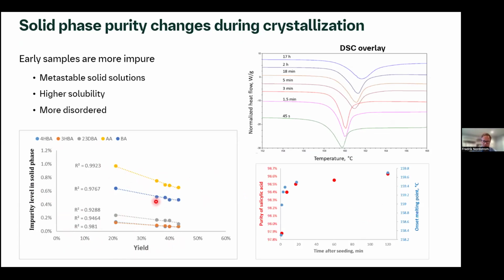And you can take these samples, right? We have solid samples here. So we analyze by HPLC, but you can also do a DSC to see what actually happens to the melting temperature and melting enthalpy. And here you see that the early samples have a much lower melting enthalpy and melting point. You can see in this 45 seconds, it slowly increases, just exactly what you expect for solid solution formations. And they're so tightly correlated that you can plot them on the same graph, and you can see that the purity and the onset melting point are very much correlated in this way.